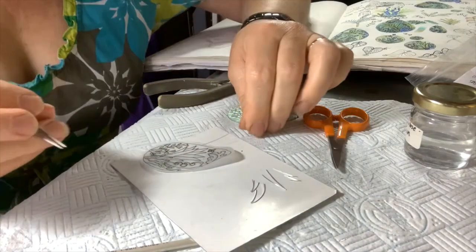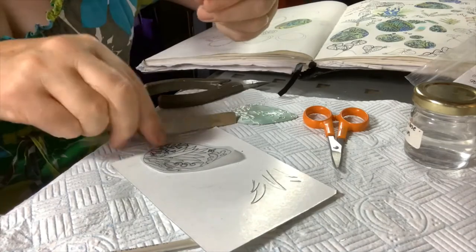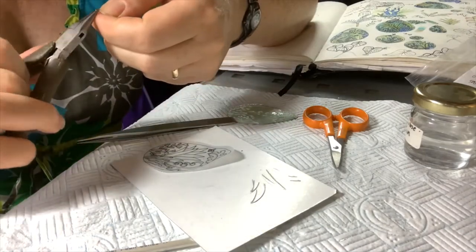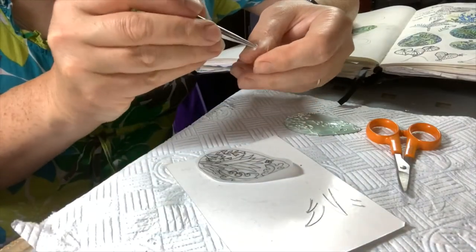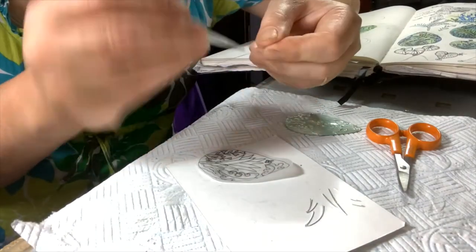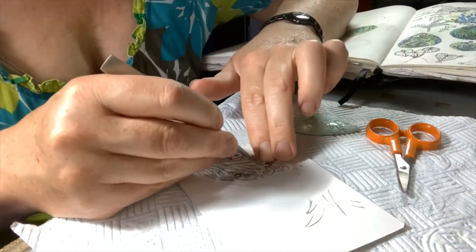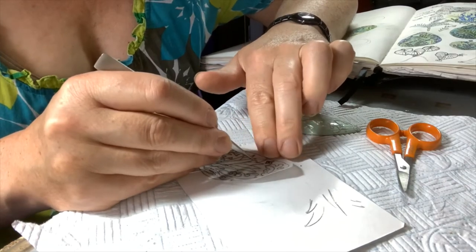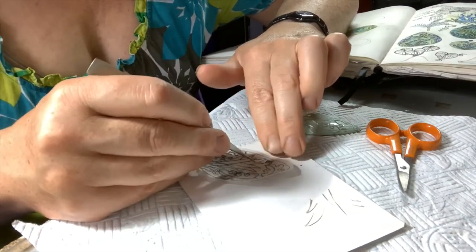These are fine silver and they will be used to outline the design and in many cases will separate the different colours. The enamel is laid in very fine layers in amongst these wires once they've been fused into place. At each stage, the layers of enamel have to be fired in the kiln at around 900 degrees for 1 or 2 minutes. And that's repeated throughout the process.